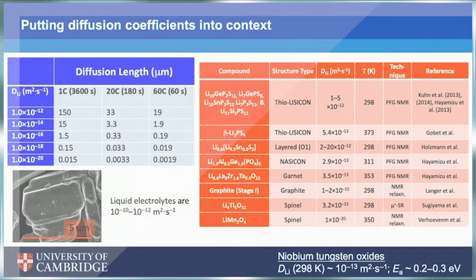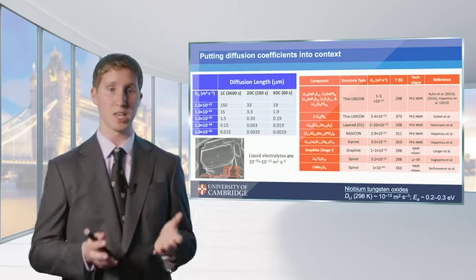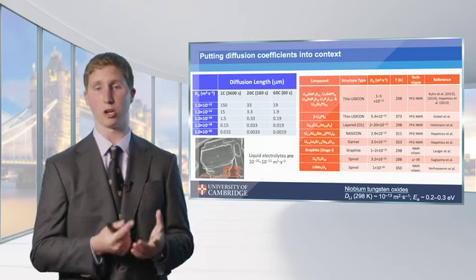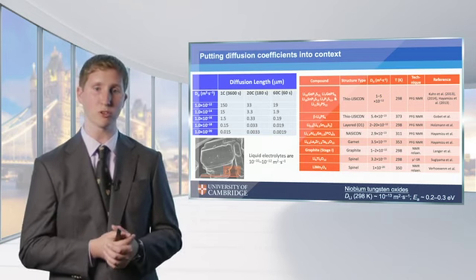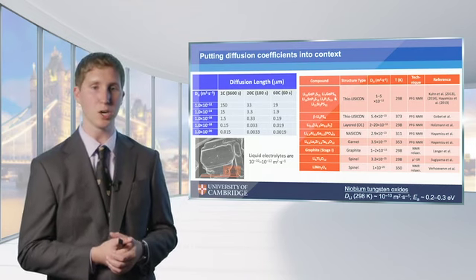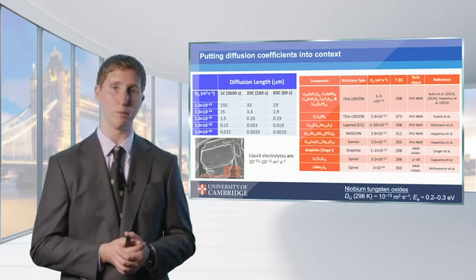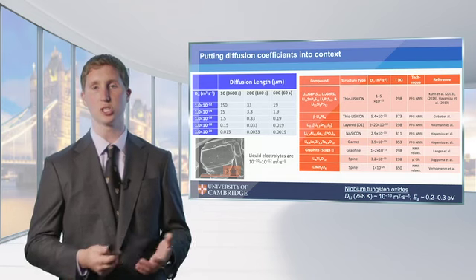And so if we think about the implications of that, you can see in the top left here, this is just a sort of back of the envelope calculation of what diffusion distance we would expect in a given amount of time for a given diffusion rate. And what we see is that, if you want to do 20C charge-discharge of your battery, then in order to do micron scale diffusion, you need to be at least 10 to the minus 14 meters squared per second for your diffusion coefficient. I'll remind you that we're at 10 to the minus 13, so we're an order of magnitude higher. So that puts us in the range where we would expect to be able to get something like, again, 10 or so microns in our 20C rate, which perfectly correlates with what we observed in the electrochemistry. And again, if you put in the numbers that you'd get for something like LTO, then it should be pushing down into the nanometer scale in what you would be able to fully lithiate and delithiate just because of the inherent diffusion coefficient.